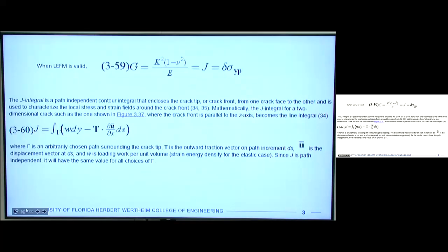So that's the J integral, and there's a lot of fundamental work done in this area to prove that that is true. And so we're not actually going to calculate the J integral because that would require weeks of computation to figure out how to do that. But I just wanted you to know the concept of this J integral and where it comes from, so that when we go into a few more empirical ways of thinking about crack propagation, you know that there is some fundamental work that's gone into thinking about how the energy is released in that material and how this strain energy release rate G and subsequently J are constants when linear elastic fracture mechanics is valid. And they are directly proportional to the square of these material properties times the stress intensity factor K.